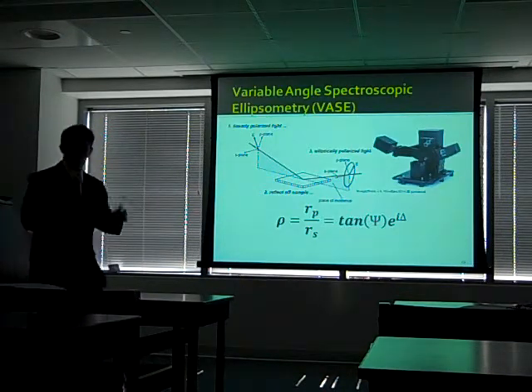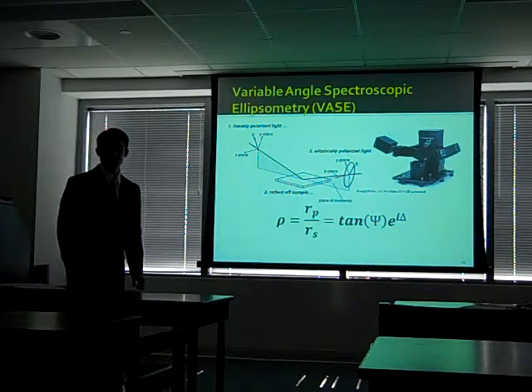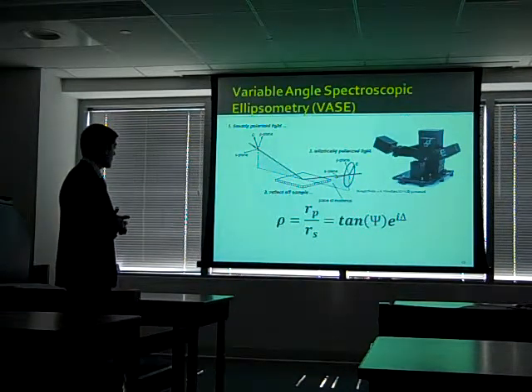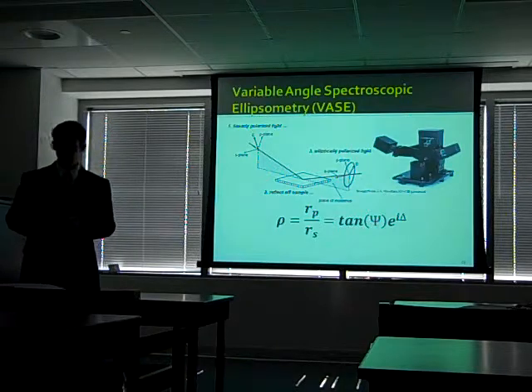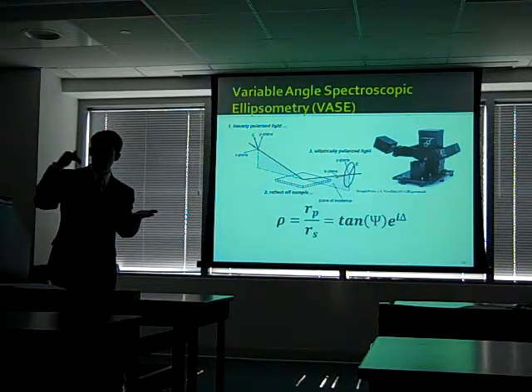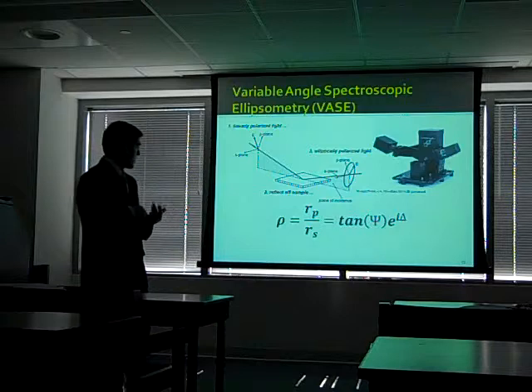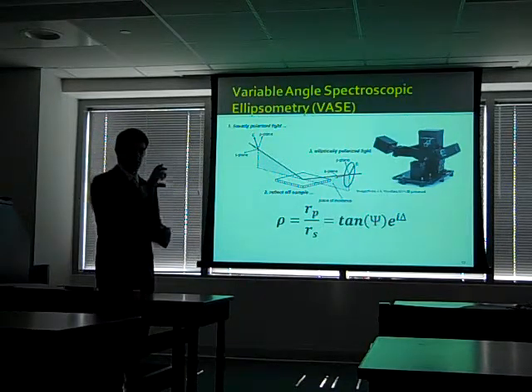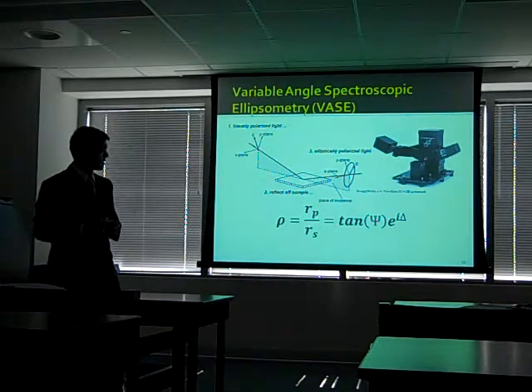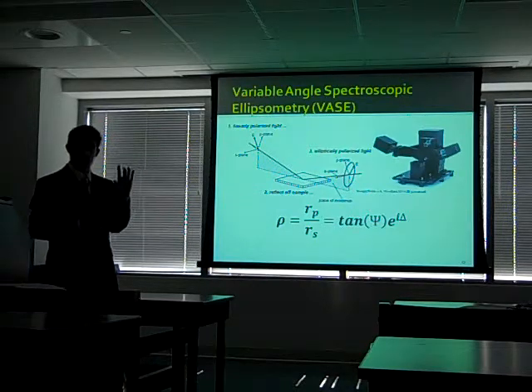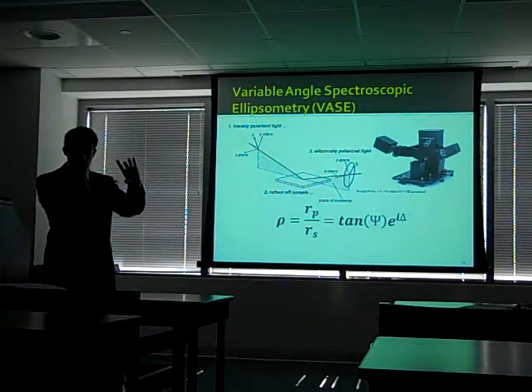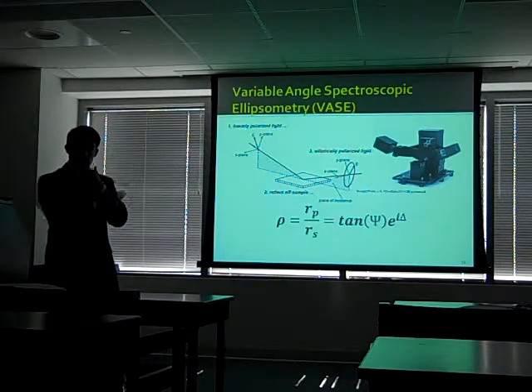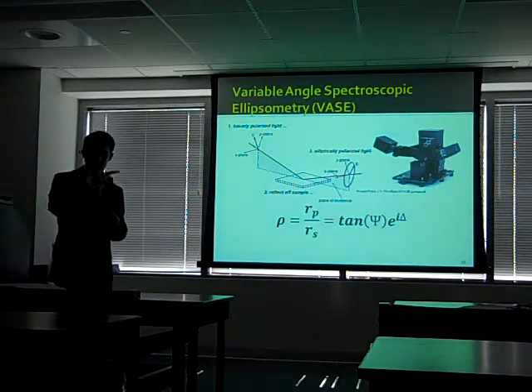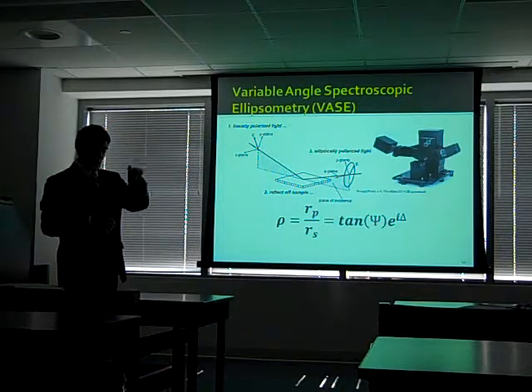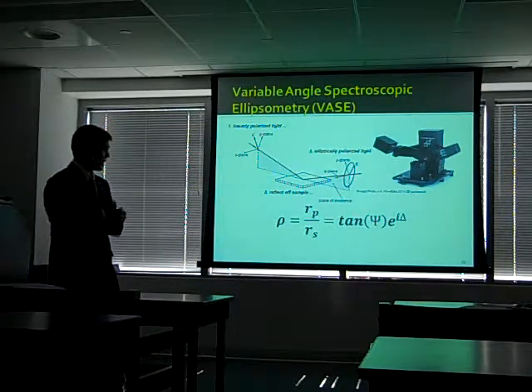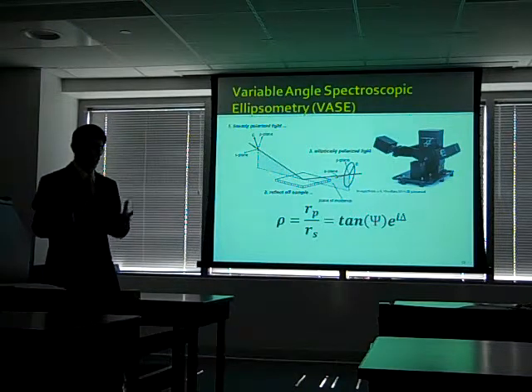Okay, so you're all wondering what's VASE. Variable angle spectroscopic ellipsometry is the technique used here. It's an optical technique where linearly polarized light is incident onto a sample at an oblique angle. The light is then reflected, and its polarization state is detected by the ellipsometer. The way the ellipsometer detects the polarization state is with a rotating polarizer, and behind that is a CCD detector. So the ellipsometer actually reads out an alternating voltage. So there's an AC character and a DC offset, and the polarizer rotates at a known angular frequency.